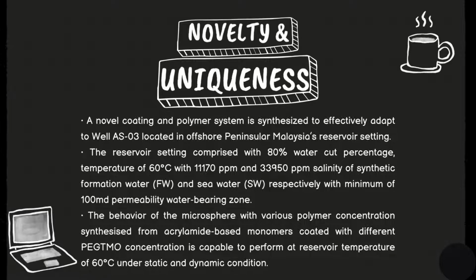Moving on to the novelty and uniqueness of this project, firstly, a novel coating and polymer system is synthesized to effectively adapt to well AS03 located in offshore Peninsular Malaysia's reservoir setting. The reservoir setting comprises 80% water cut, a temperature of 60 Celsius, with 11,170 parts per million and 33,950 ppm salinity of synthetic formation water FW and seawater SW respectively, with a minimum of 100 millidarcy permeability water-bearing zone.